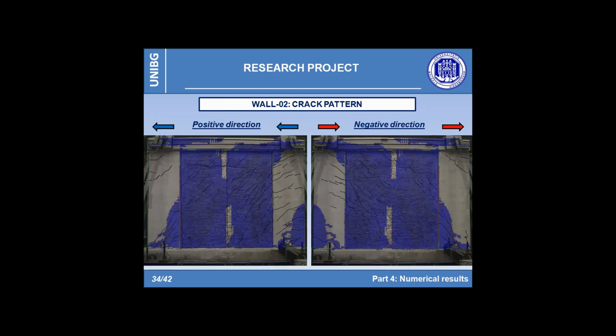As usual, the superimposition between the experimental crack pattern and the numerical one is now presented, distinguished between what has been observed during the application of the semi-cycles in positive and in negative direction. The result of the superimposition is very satisfactory, proving that the analysis is able to reproduce the different mechanisms.